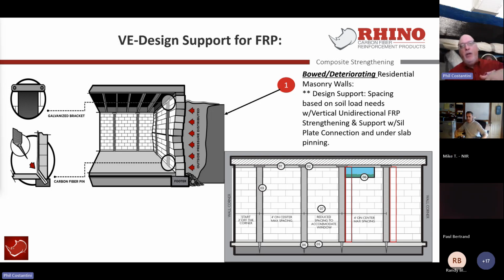And you drop it in there, and then you use the raw material to flare it back into the strap while you dowel it back down. It's almost like a stirrup detail with a steel bar. You're dropping it in there, and it's the exact same thing, Mike, except you're not doing the roll-up thing. You're just taking the raw material and cutting out the fabric that's holding it together, and you just squish it together and then drop it into the anchor.